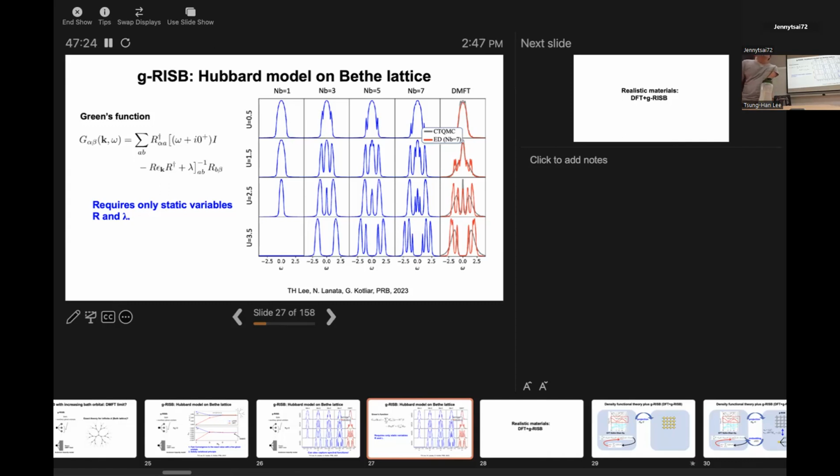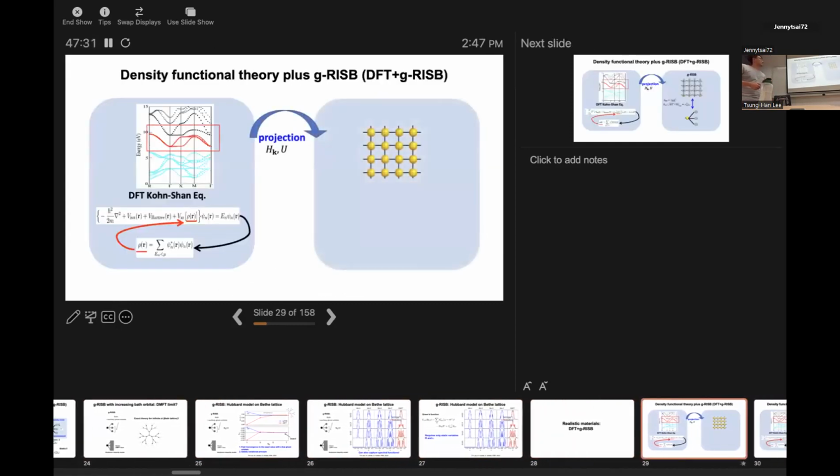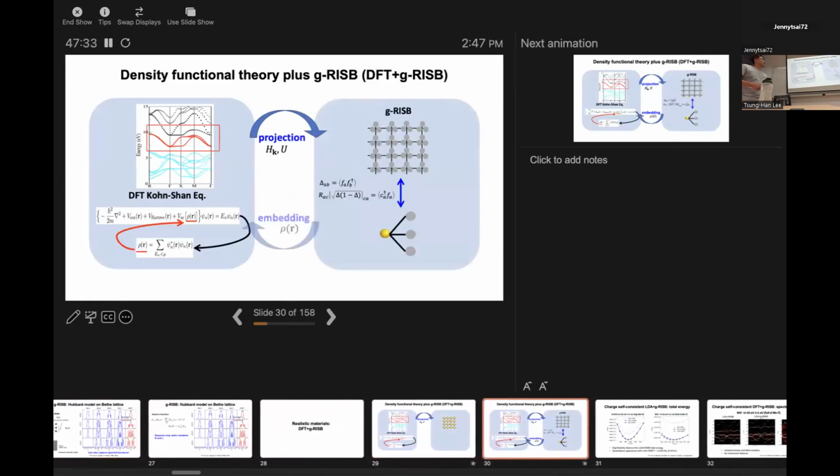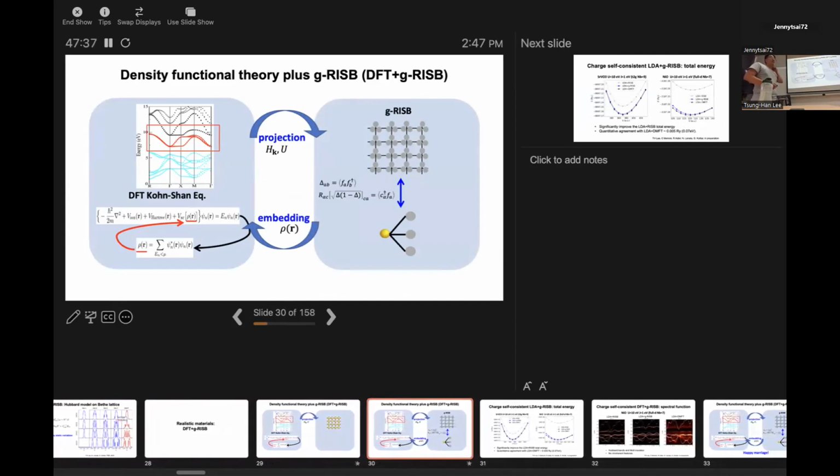DFT people talk about DFT plus U. What's the difference from DFT plus U? Oh, yeah. So DFT plus U can be viewed as a specific case of our approach. If we don't include ghosts, and we solve a dimer, and then we solve this problem using Hartree-Fock, then we will get DFT plus U. Yeah, so it's kind of included in our theory.